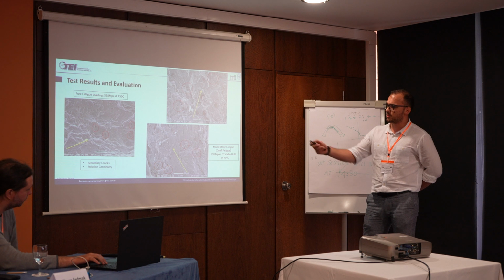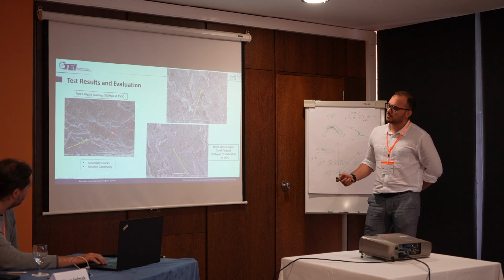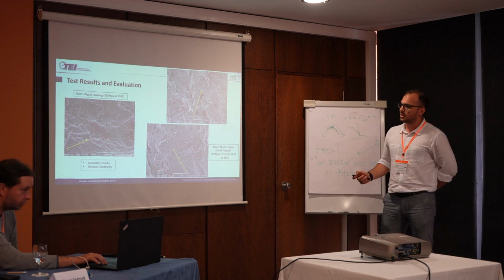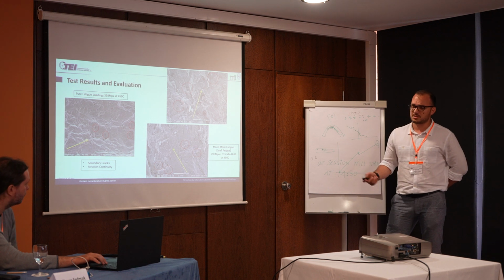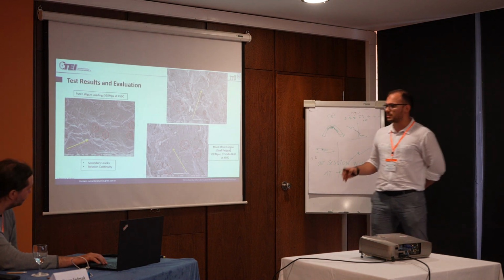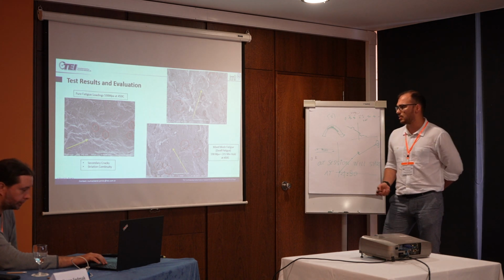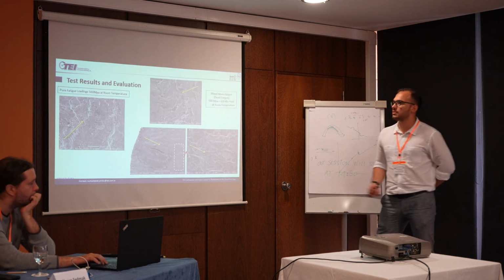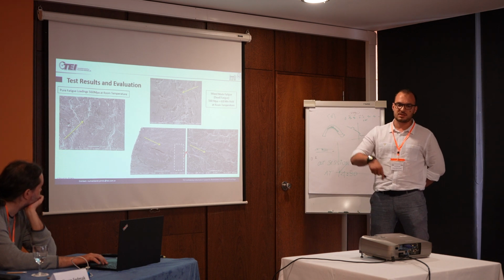We can move on. So with the SEM analysis at the higher temperatures, dwell and non-dwell tests, however, we see similar features like secondary cracks. This one is a non-dwell test, and these two are dwell tests. The secondary cracks seem to have increased, but it's not certain. We observe them in both cases at high temperature tests. We can move on.